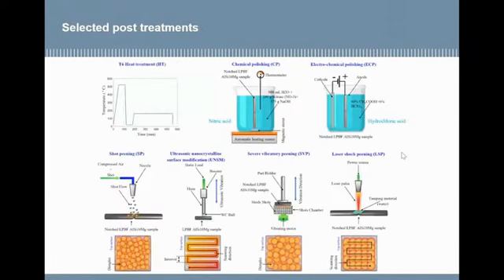Here you can see an overview of the treatments that have been used, including T6 heat treatment, chemical polishing, electrochemical polishing, shot peening, ultrasonic nanocrystalline surface modification, severe vibratory peening, and laser shock peening. So we have been applying each of these treatments individually and also their combination with the heat treatment.